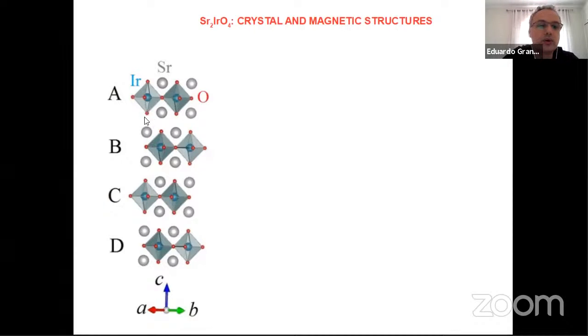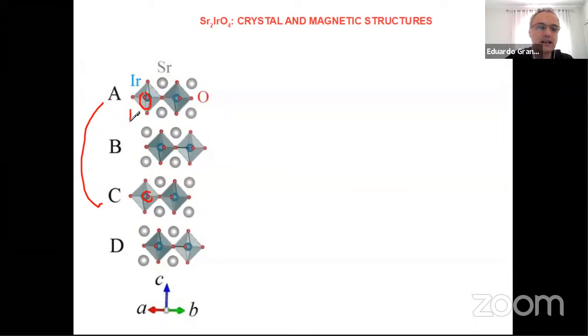oxygen octahedra. So you may see here, for example, this oxygen atom in layer A is tilted. You see it from the left, but then in layer C, it has the same glide with respect to layer A, but you see that the oxygen atom is now tilted to the right. So you have a tilting pattern between layers A and C, but in between layers A and C you have layer B, which has a glide plane, which is slid with respect to layer A.